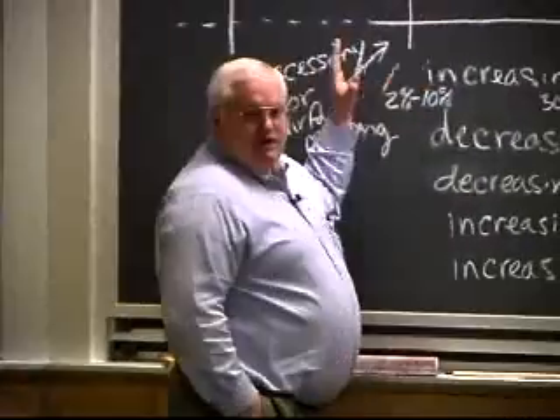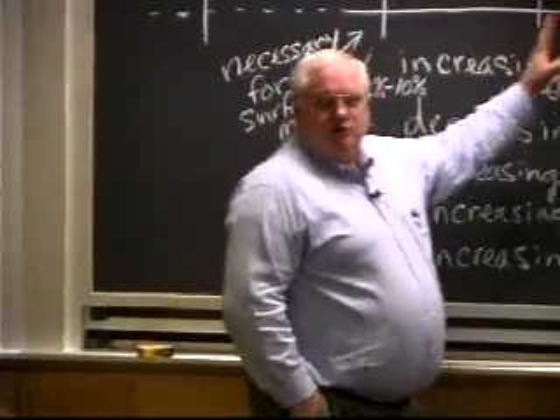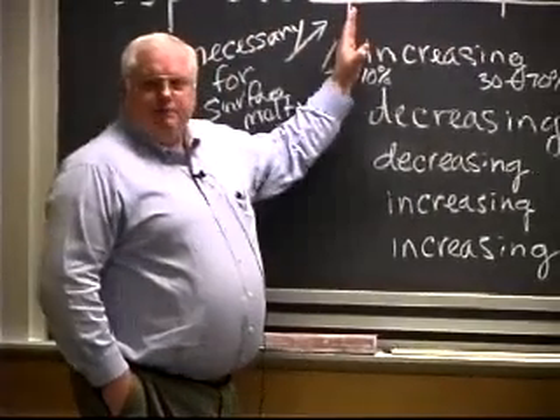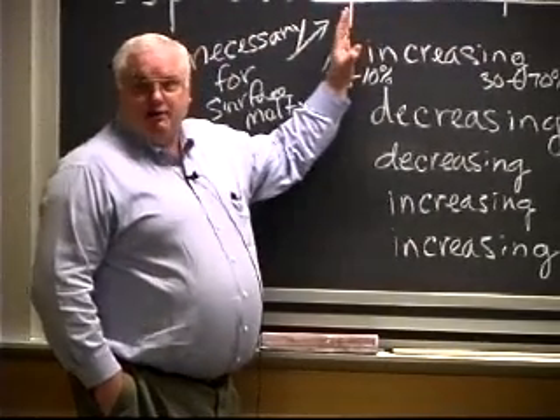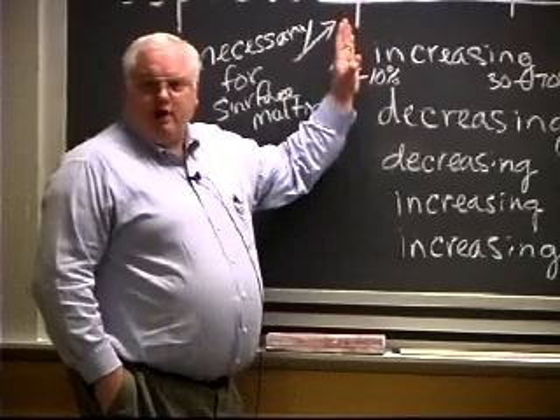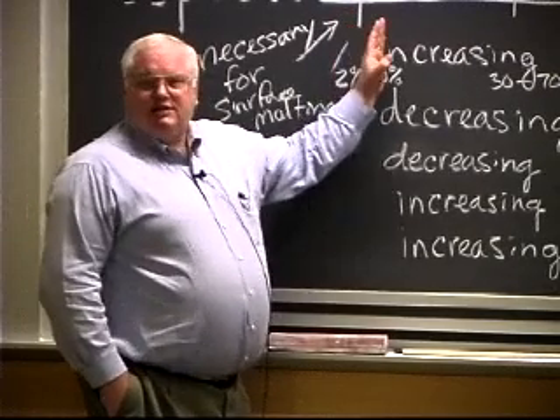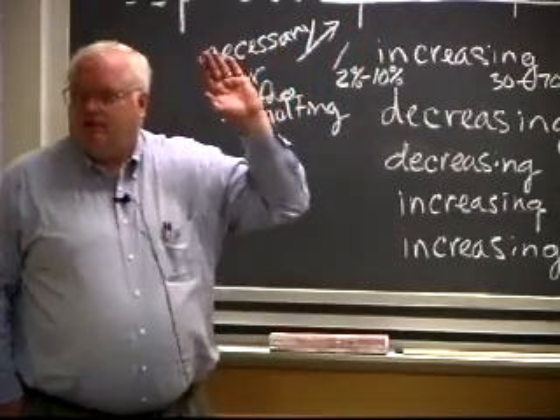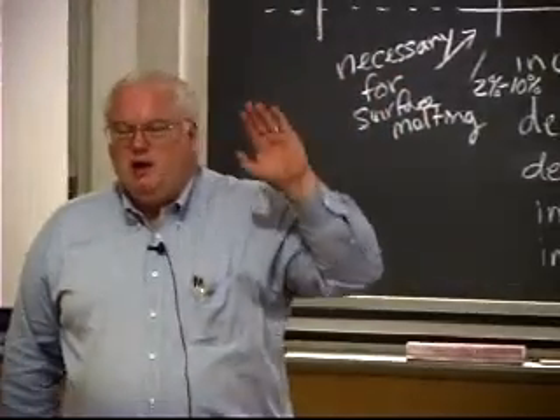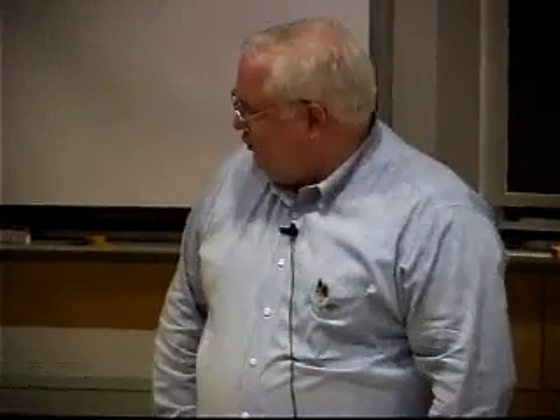It turns out plutonium has a very, very low thermal conductivity, so it takes a long time for heat to diffuse into it. This was actually an arc weld on plutonium, and it's more like a ceramic or even an insulator. It has lower thermal conductivity than many ceramics, so the heat doesn't diffuse in a normal amount of time, and it ends up with almost no heat affected zone. So for whatever that's worth, next time you're looking at welds on plutonium.